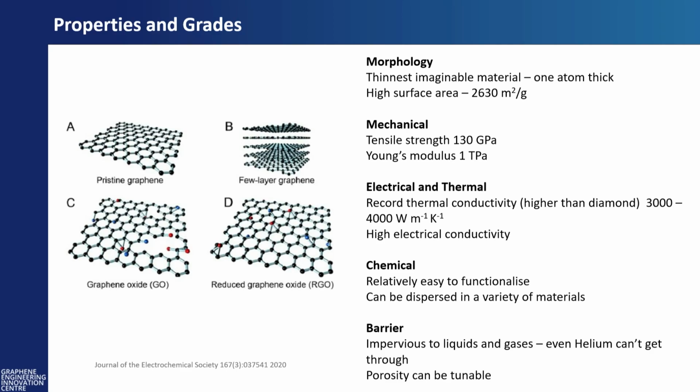Also, we've got functionalized graphenes. One of the major functionalized versions that we use is graphene oxide, where we put different oxygen-containing groups onto graphene. That could be hydroxyls, carboxylic groups, epoxies, a random assortment of, apologies to non-chemists, oxygen groups, and that can help the graphene to interact with whatever you're putting it into, whether that's cement, a polymer, a coating, or what have you. You can also reduce this back down to graphene if needed, which has other properties which I won't go into.